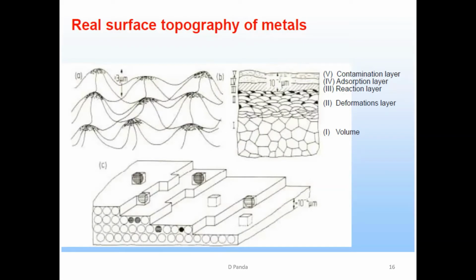That's why yesterday sir told you we have to do HF dipping, hydrofluoric acid dipping, for the silicon substrate, because we need to remove this contamination layer. It is usually a few angstrom, not nanometer, about 5 to 6 angstrom, 10 angstrom maximum. It can be removed by dilute hydrofluoric acid. So before we deposit the film, I will tell you what a film is after a few slides. This film will be deposited on the adsorption layer, and this adsorption layer is controlled by the reaction layer. So all these things are important for the device.